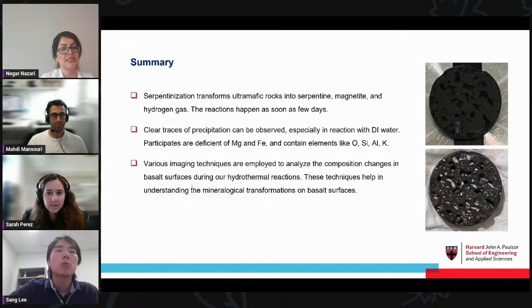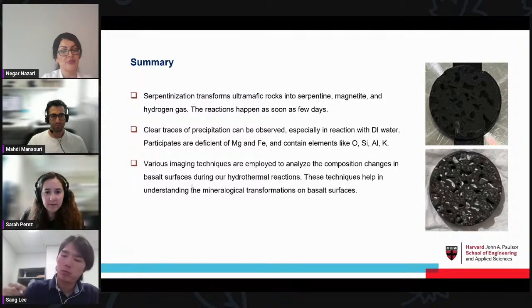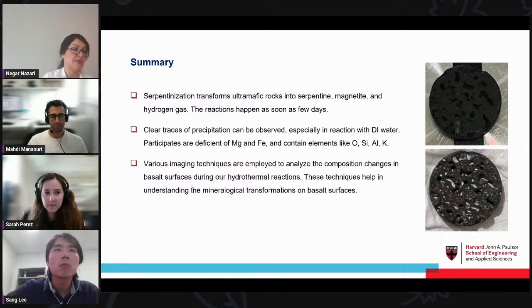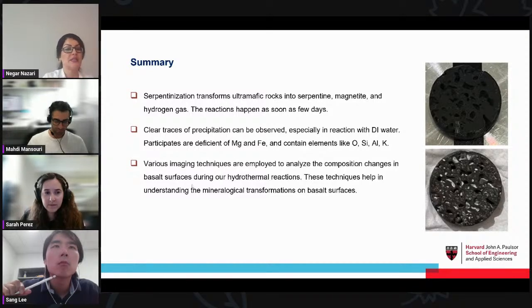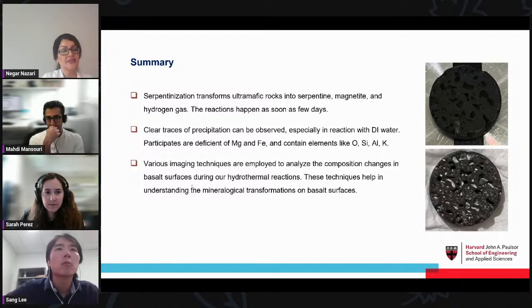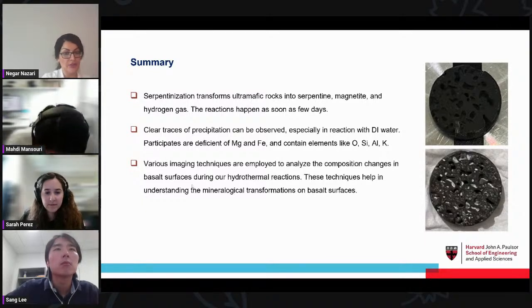So in summary, we showed that serpentinization transforms ultramafic rocks into serpentine, magnetite, and hydrogen gas. We didn't prove the presence of the hydrogen gas, but we proved the changes that happen across the minerals on the surface of the sample. The reaction happens in as little as a few days, which is very interesting. And clear traces of precipitation were observed, especially in reaction with the DI water, which was expected. The carbonate will react faster with the DI water, and also clay will react more.